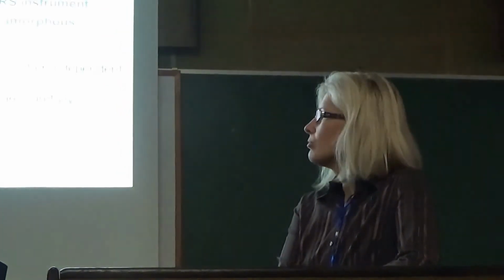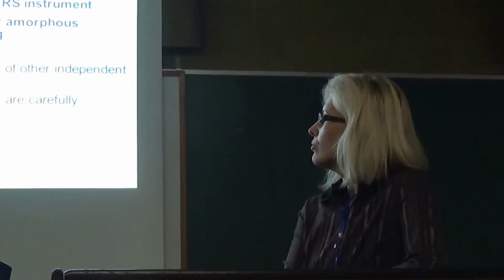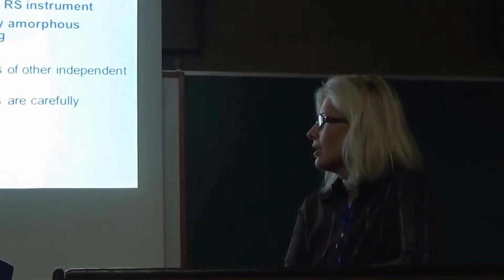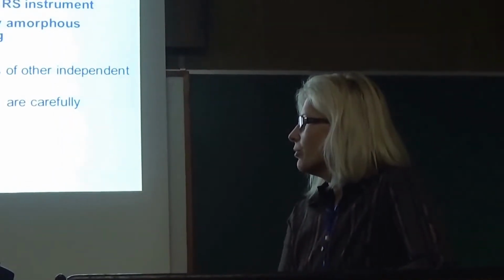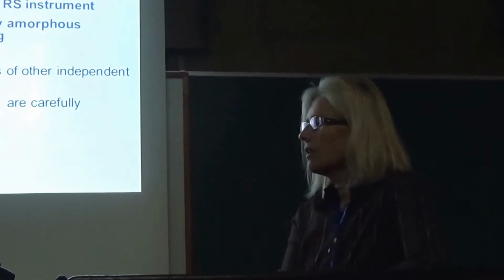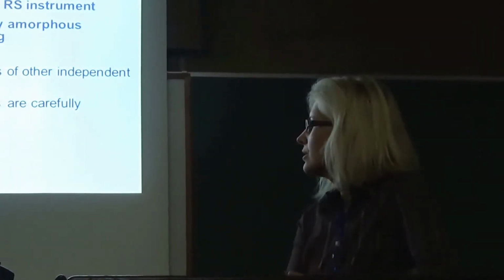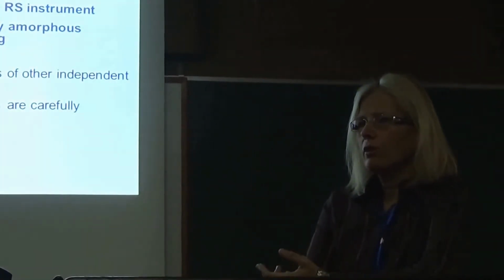Luminescence can be detected with a Raman instrument. We can study amorphous or nearly amorphous material. But it is very important to stress that reliable results can be achieved only if you take care during your instrument use - about intensity of your laser, about the position, about good focusing, and so on.